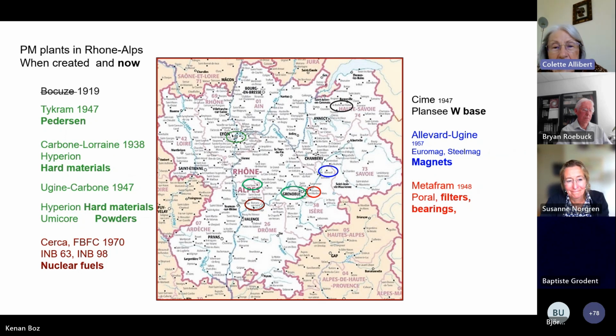But what has been important also, I know that it seems to be far from the application, but however, I think it has been very important, was the contribution to the control of the microstructure by the fine analysis of images and of the interface. And all the work that was done showed, but it was difficult to analyze, the strong relation between the powder production process and the hard material constitution and microstructure, and the strong contribution of the interfaces.